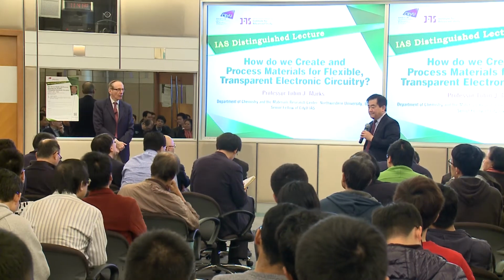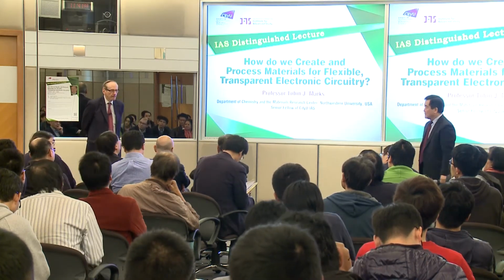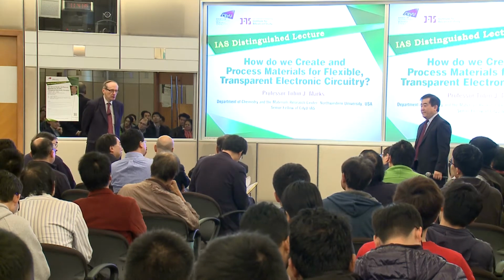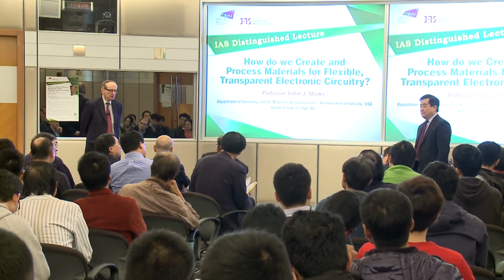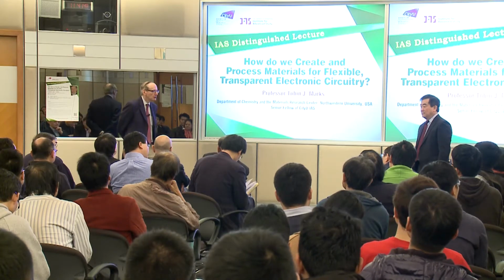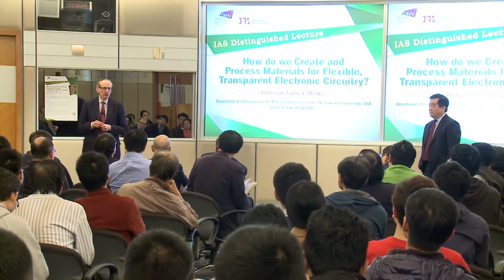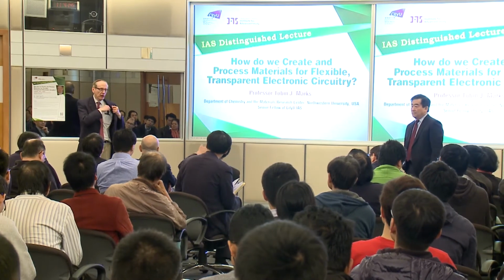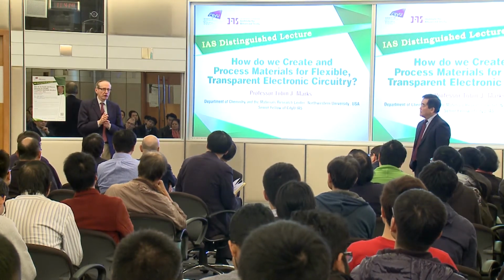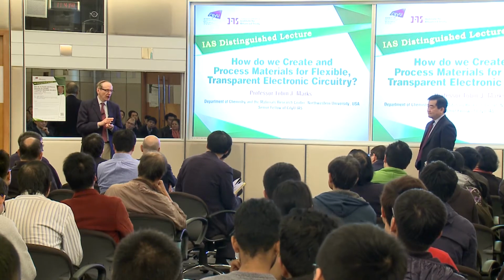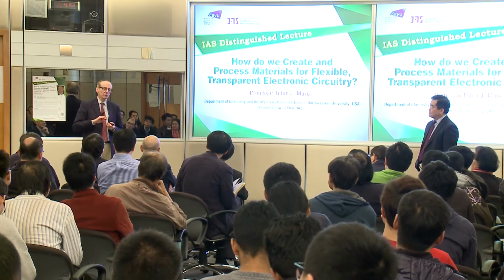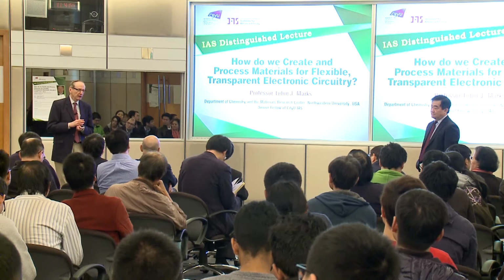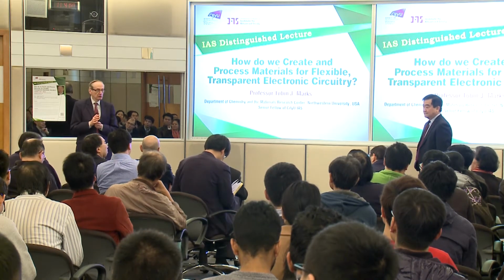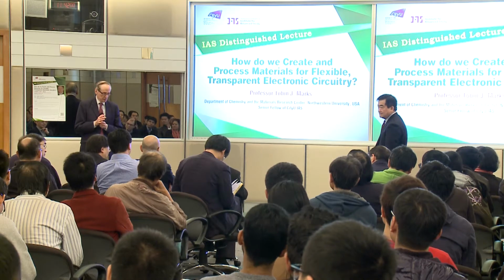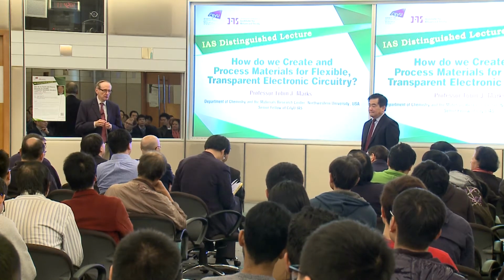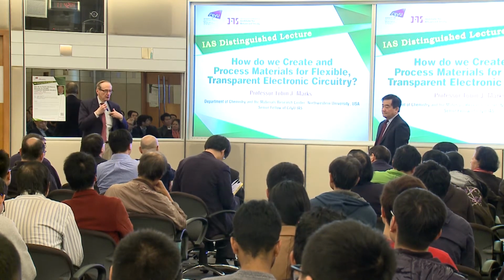Let me ask a mechanical question, okay? You have so many layers here, including oxide. You bend it. How much strain is generated? Why didn't this oxide crack? Do you know why? Oh, there are no grain boundaries. It's amorphous. And the oxide layer is thin. For most of the transistors, 50 nanometers thickness will give you enough current to light up an OLED or something like that. So they're quite thin, and that's very important. When the oxide is very thin, it can bend about 6-7% without cracking. Still all deformed in the elastic range.